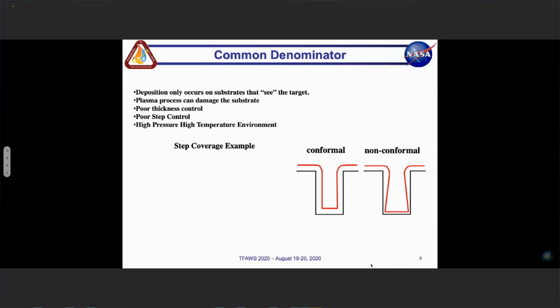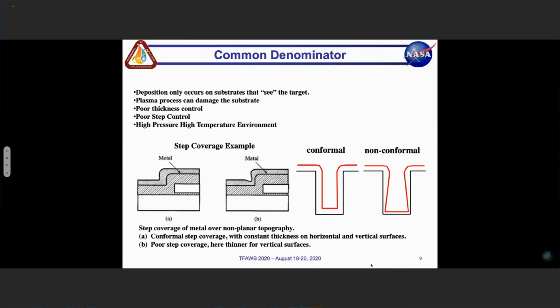In all those particular cases, the previous three, there's a common denominator. Obviously, the deposition only occurs on substrates that see the target. You do have a plasma process which can damage that substrate, which could be very dangerous. You have poor thickness control, poor step control, and you need a high vacuum, high temperature environment.